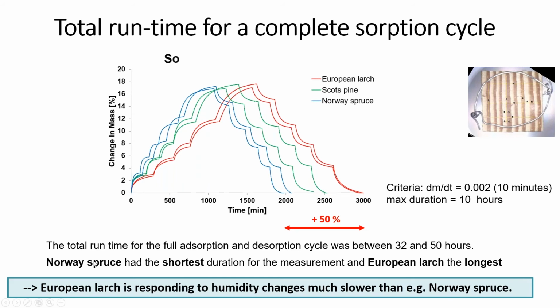And so the results, quite interesting: if you compare larch to spruce, the larch took 50% longer than the spruce. So Norway spruce had the shortest duration, where the European larch had the longest, because then you start thinking about why is that the case? Because there's density differences and so forth. But the pine has quite a similar density. Larch is still different. So European larch is responding to humidity changes much slower than Norway spruce. One detail that I haven't seen too much in other references.